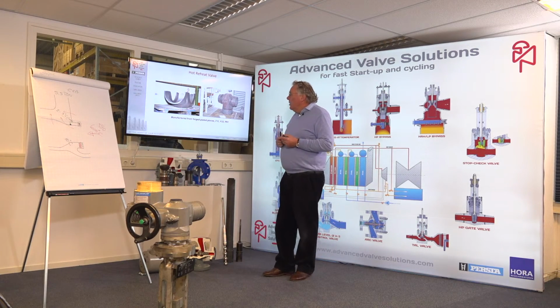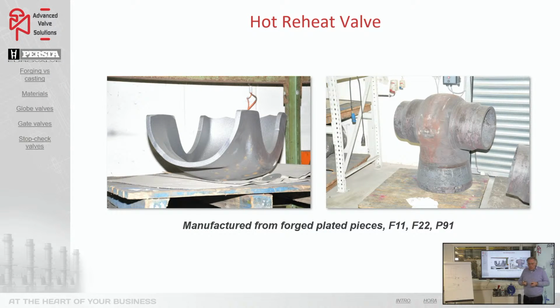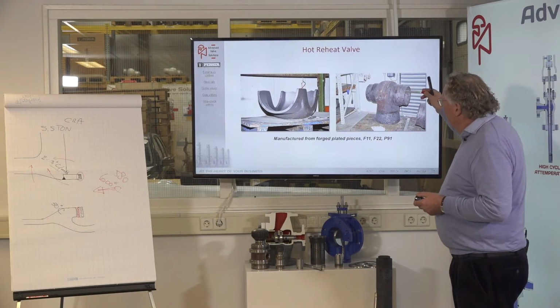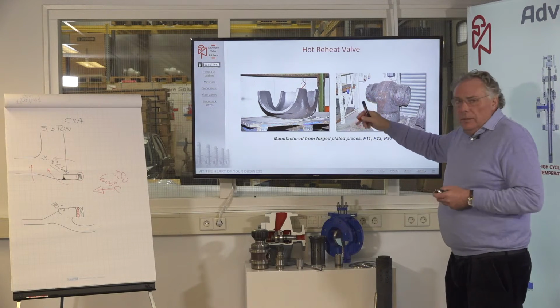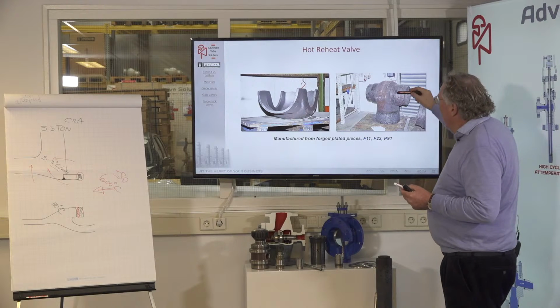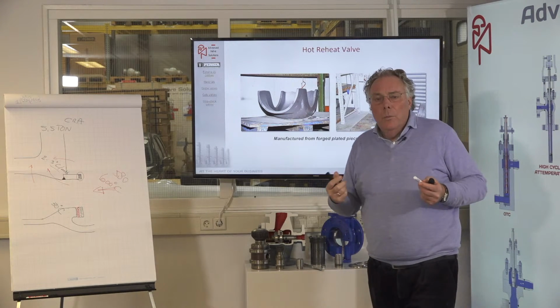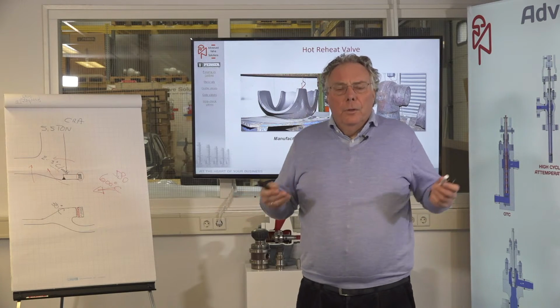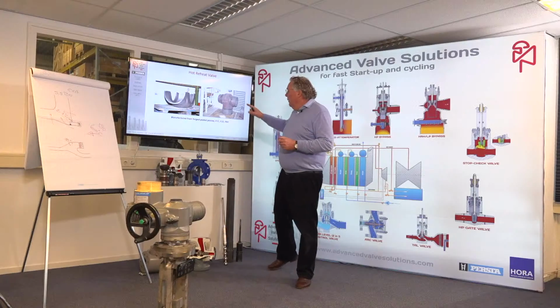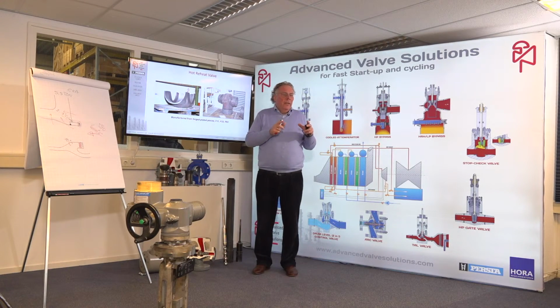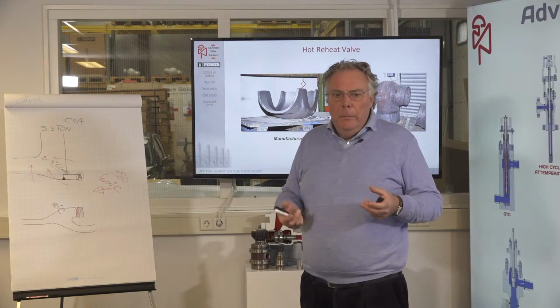On the picture left you can see pressed half shells, where I take, in the old days, a C12A casting of 5 tons and a lot of repair welds to compensate the casting failures in that casting. I now take a 2.5 inch thick piece of P91 plate material and I weld this body together. And I have 2 of these half shells. It takes a little bit of imagination, but nevertheless I end up with this valve. This valve with a pressure seal has a weight of, let's say, 1.5 ton versus a cast valve of 5.5 tons. And the wall thickness of this valve is basically roughly the same as the wall thickness of your pipe wall, of the hot reheat pipe. So basically this valve can ramp up and can cool down extremely quickly as well.